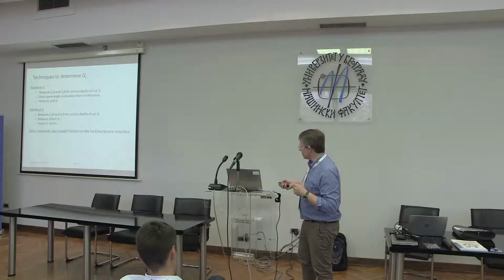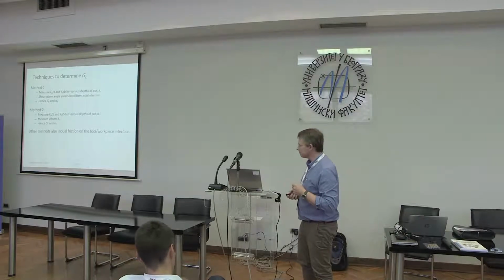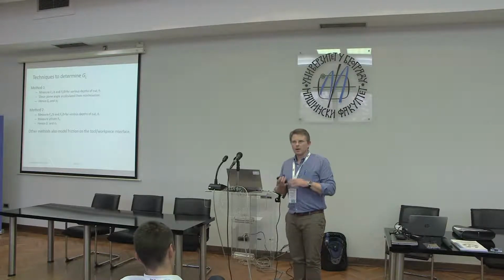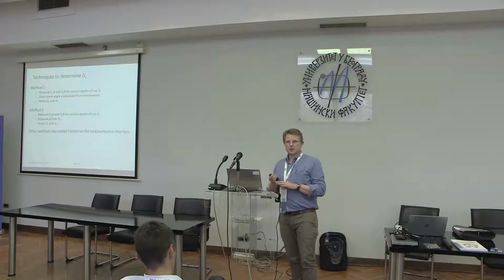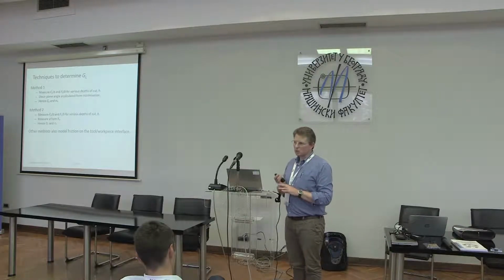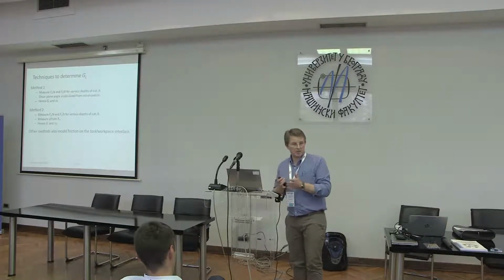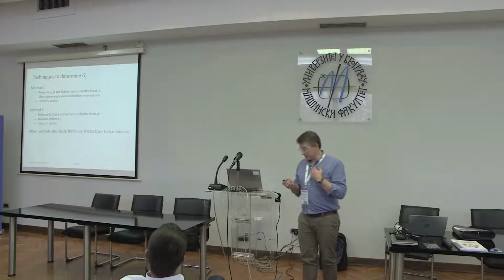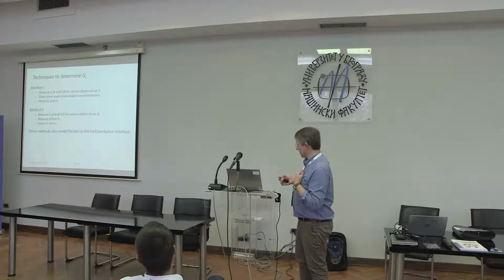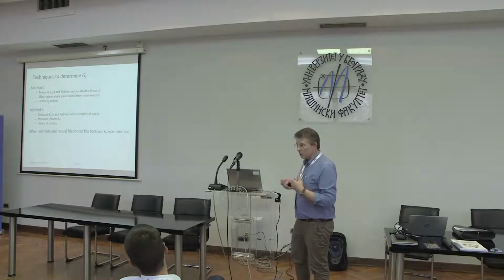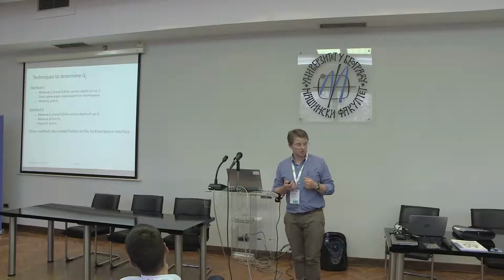So you can do that, you can measure the chip thickness, or you can say, well, what's going to happen is that the shear plane is going to form on an angle which minimises the cutting force. It's like an energy minimization requirement. So that concept was used by Merchant in his initial cutting analysis for metals. We used it and found it worked extremely well also for polymers.